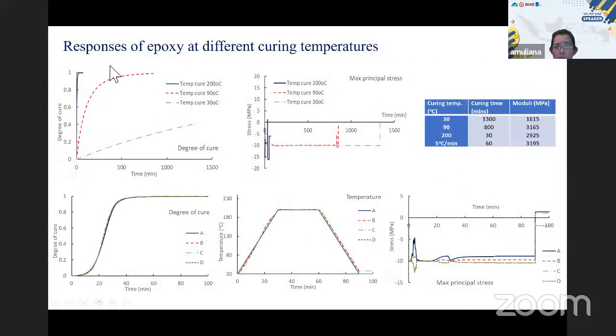Just to compare, when we cure it at a different temperature or lower temperature, you can minimize all those effects. However, with lower temperature, it might take longer for you to cure, right? So this is just to show you the table. When we do it at room temperature, even after 1300 minutes, it's still not cured. So when we go with the higher temperature, it cures faster. But one thing though, when we compare this at 90 degrees, the modulus is slightly lower at 200 because of the build up in the residual stress that would reduce the modulus of the polymer.